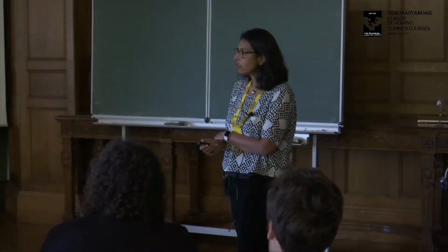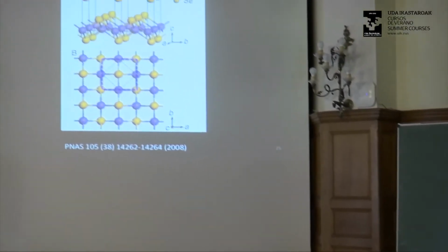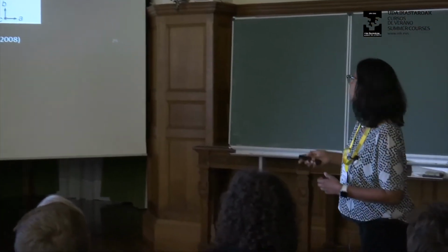So this is the crystal structure of this compound. You can see it's a layered material. One interesting thing is, so these purple balls are iron. And if you look at it, you have selenium here, which is on top, and then you have these seleniums that are on the bottom. So when the crystal makes a choice, whether these seleniums are going to be on the top or the bottom, and in fact, you'll see this is really important because this provides an opportunity to get crystalline domain walls where the selenium switches from the top to the bottom, right? You can imagine these kinds of defects occurring naturally as the crystal is grown.